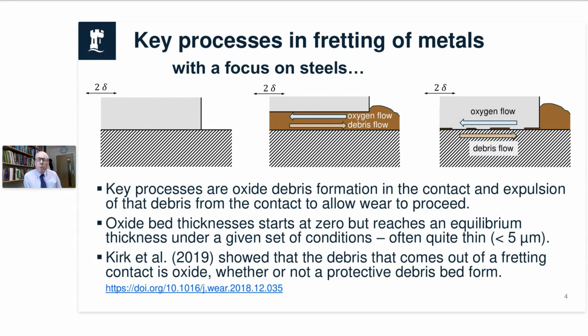So what is going on to allow that to happen? Remember, this has to happen across the whole contact. You can't have nothing happening in the middle, because in the end the wear would stifle. And so what we need is oxygen flowing in to the center, because we know that everything that comes out, in pretty much whatever conditions in these kinds of tests, we measure this. You can extract the debris and look at it, and there's a reference there at the bottom. And we see that the debris that comes out is oxide. It's not full of metal. It's full of oxide.